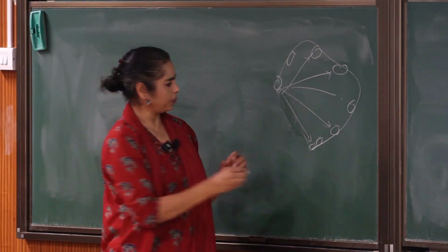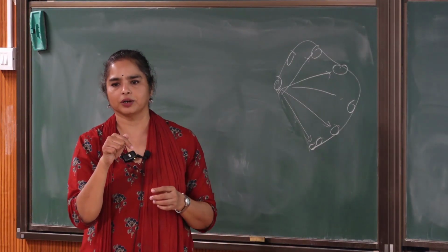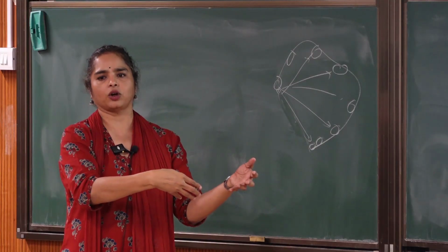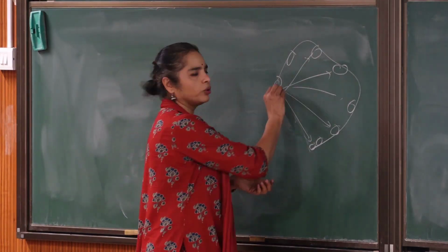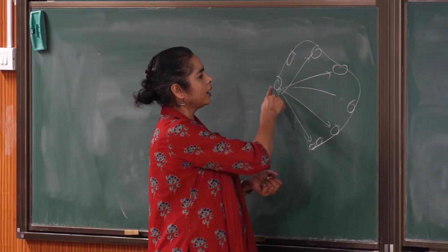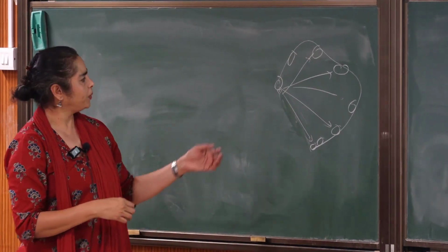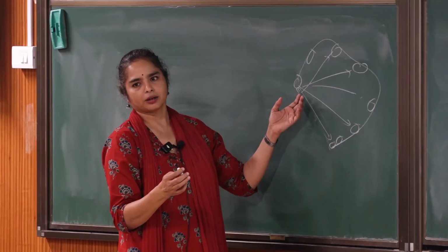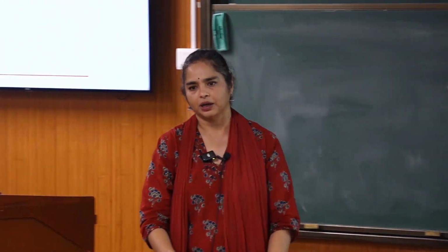If I change from good solvent to poor solvent, it's the polymer that is doing the work. Either it likes the solvent or it likes itself. But here the polymer has no role. It's the crowder, and I can tune this. So beyond a critical point, too much of a good thing, they want to come closer. Then there is a collapse that happens.